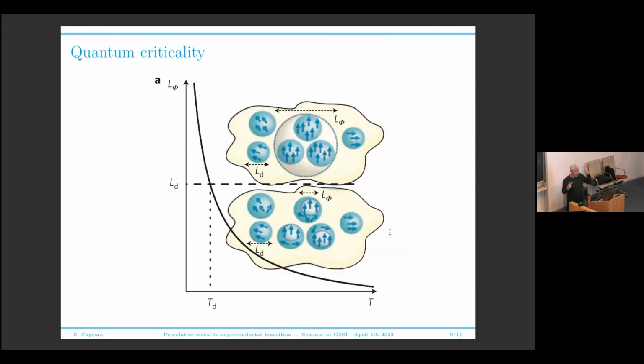Well, this is so because you have two lengths in your system. One characteristic length scale is the typical size of your superconducting island, say a given number, LD. And then you have another scale which depends on the temperature, the coherence length. Now, when you start from high temperature, your coherence length is much smaller than the size of a superconducting island. You now lower the temperature and the coherence length increases until it reaches the size of your superconducting islands.